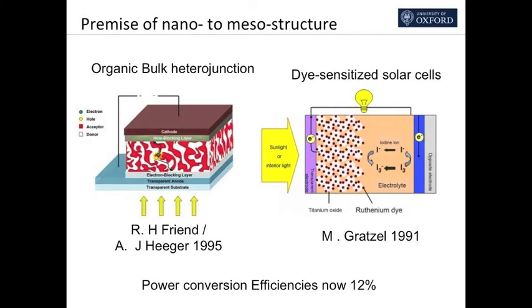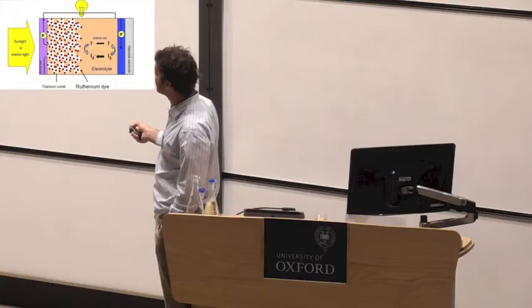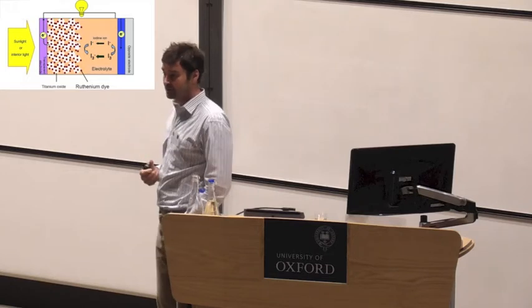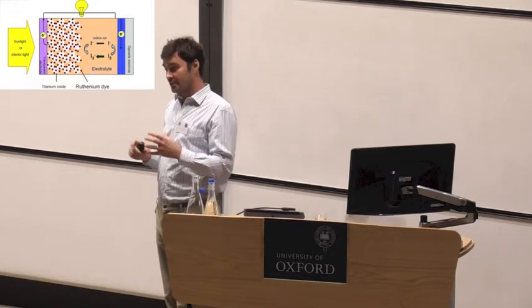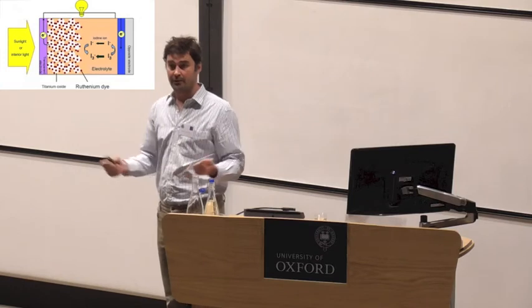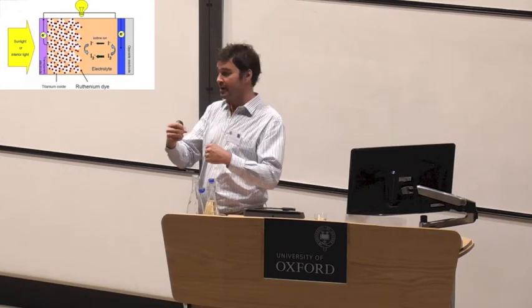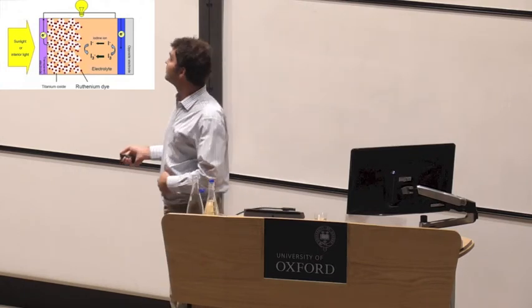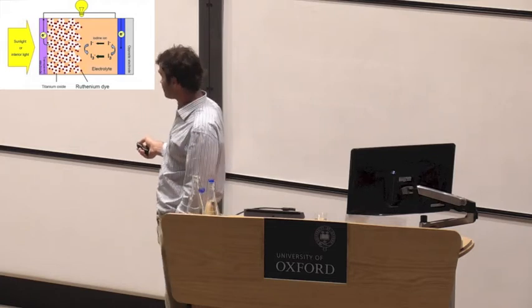I'm not going to go into the details, but instead of having a solid layer of organic absorber, there's two materials, the P and N type material, all mixed together. This enables charge to move out of the P-type material, out of the positively charged material, into the negatively charged material, and get out of the device. If you try to make a solid layer of an organic absorber, all the charge doesn't get out. The charge can't transport that far. They actually form what's called a tightly bound exciton, for anyone who's interested in the more details.